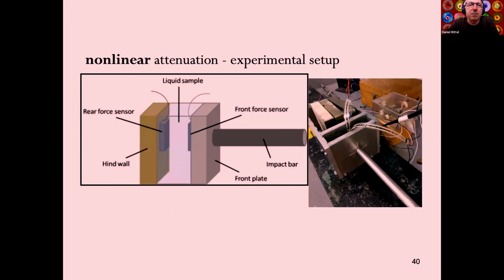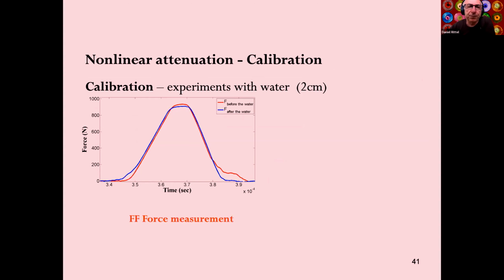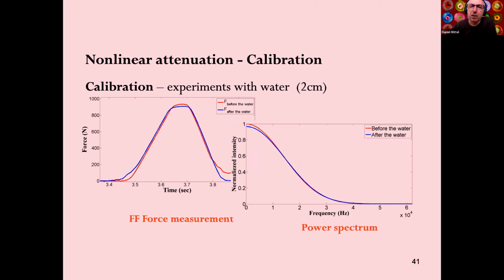Let's go to a more exciting part, the nonlinear attenuation, in which you apply a shock and you would like to see the attenuation. A priori, it's not supposed to be the same as the linear one. So again, you use your setup with a liquid sample. We have a liquid sample, 2 sensors, and you sample the front and the back forces with your sensors. Start with water, as always: no attenuation, that's expected. That's the power spectrum as a function of frequency.